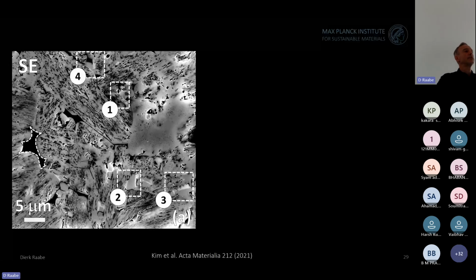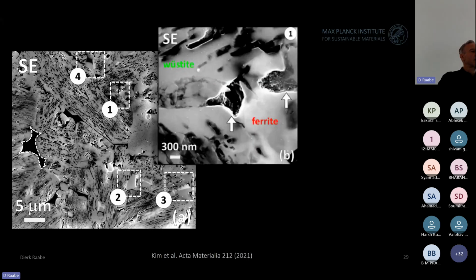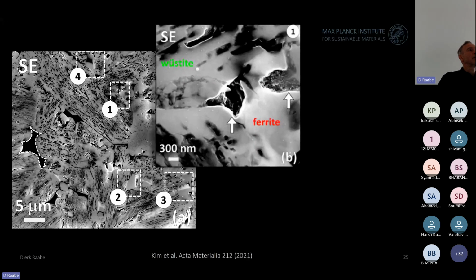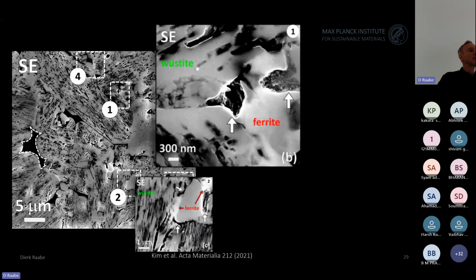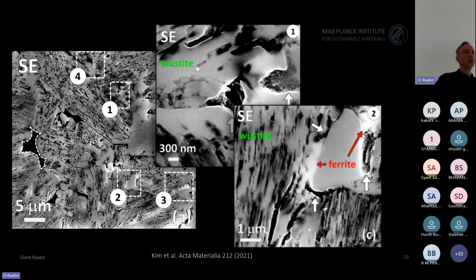When you look into these partially reduced pellets, like you see here, and you can find the details in this Acta paper that I'm showing you at the bottom of the slide, you can see that you have a complex interplay of the phase transformation, of the porosity, and so on. And I only show two patches here. You can see many, many more details, of course. And you can also see that you even have delamination, fracture, and so on. That means, in part, you also create new surfaces.